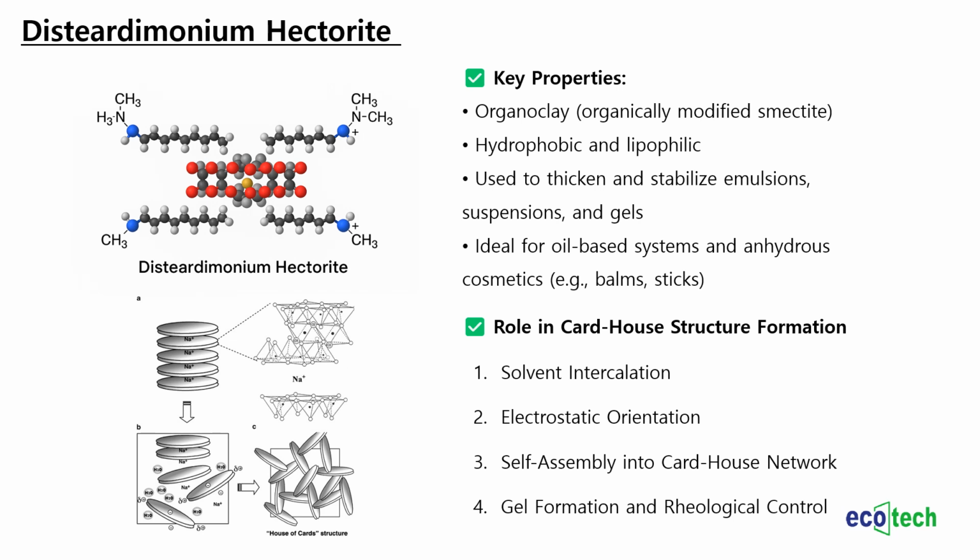When used with a propylene carbonate polar solvent, this solvent interacts with the clay layers, weakening the electrostatic forces and exfoliating the layers.